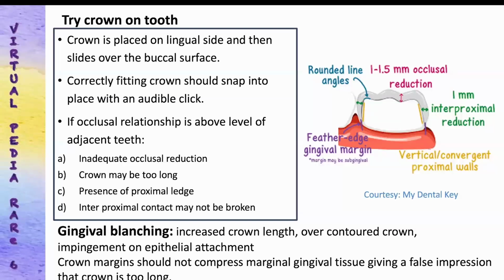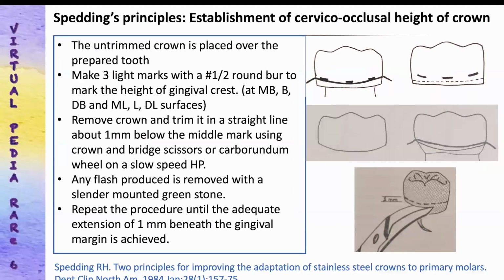And if you find that the crown is a bit high, that means your occlusal clearance is not sufficient. You've not reduced it occlusally enough. The crown may be very long. There could be a proximal ledge. You've not broken the contacts at all. And please be careful about gingival blanching, because excessive gingival blanching could indicate that the crown margins are impinging on the epithelial attachment. So for this, how do you establish the cervico-occlusal height of the crown?